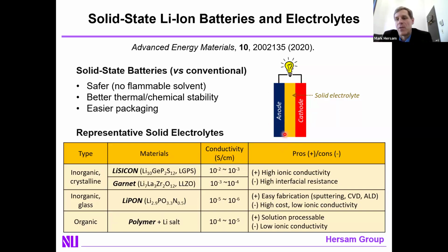And this would, of course, be of high interest, particularly from a safety point of view, because it's the liquid electrolytes in traditional lithium-ion batteries that present the flammability hazard, which is the most catastrophic failure of a lithium-ion battery. In contrast, if you get rid of the liquid and only use solids, then of course you dramatically improve the safety of the battery. Of course, this is not a new idea.